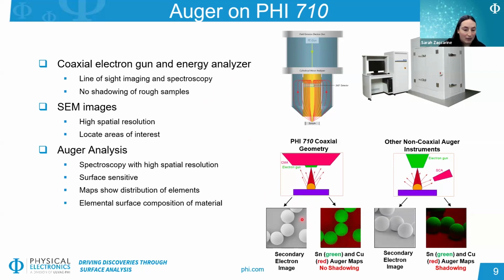In this example, we have an image and a map of particles, and you can see we're going to be getting electrons coming off at all sides of the particle. Because of this geometry of our system, we can analyze those more effectively and get a much nicer image and map compared to a non-coaxial geometry where you can see we have a lot of shadowing because you're not detecting a lot of the electrons coming off on the opposite side. So with this setup, we can get high spatial resolution SEM images, which can be used to look at morphology, find areas of interest, as well as Auger analysis, both spectroscopy and mapping of elements with high spatial resolution to look at the composition across the sample.